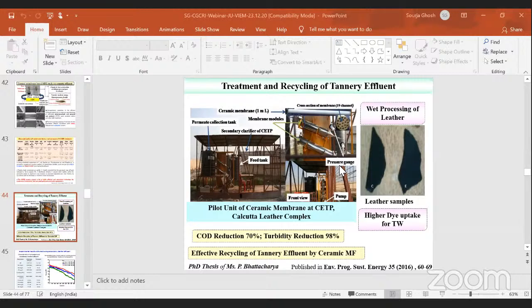And this water was studied for reusability in the wet processing of leather. This study was done in collaboration with the Central Leather Research Institute (CSIR) CLRI, wherein the treated water and fresh water were both used. The fresh water system was used as a control. The process enabled COD reduction of 70% and turbidity reduction of 98%, and higher dye uptake was obtained for the treated water sample. So this is the leather piece dyed with the experimental, that is the membrane treated water, and this is the control fresh water sample. Significantly higher dye uptake was obtained in this leather sample.